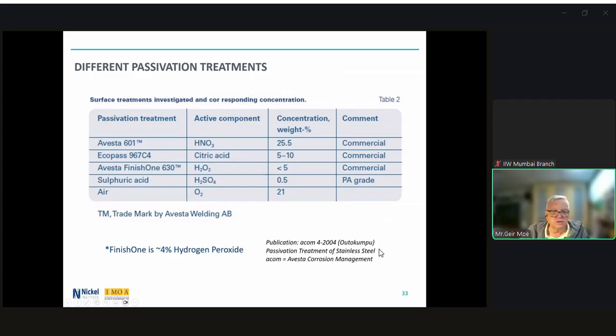So a few slides back, passivation was defined as a surface decontamination process that is not corrosive to the stainless steel, but simply removes surface contamination so that the clean stainless steel surface can spontaneously form its passive layer. Here we are going to see what degree of corrosion resistance is achieved after various passivation treatments. Those treatments being nitric acid, citric acid, hydrogen peroxide, and in this table, Avesta FinishOne 630 is a hydrogen peroxide solution, and a dilute sulfuric acid, and simply oxygen and air, the last one in the table. This work was performed by Avesta, now known as Outokumpu, a major European stainless steel producer.